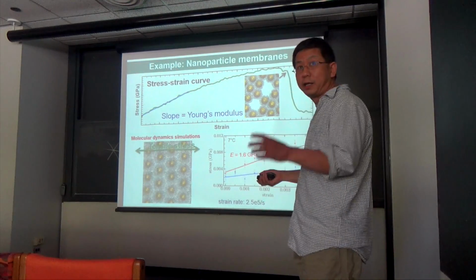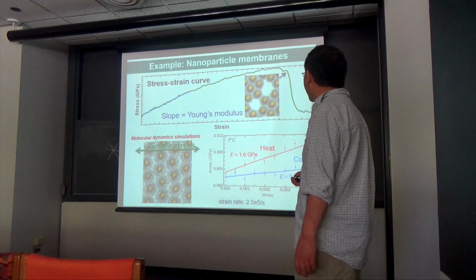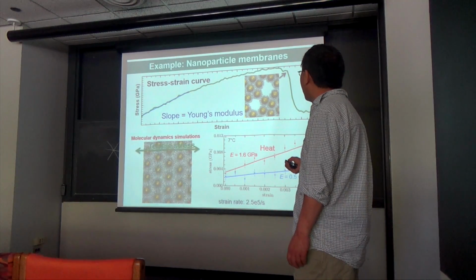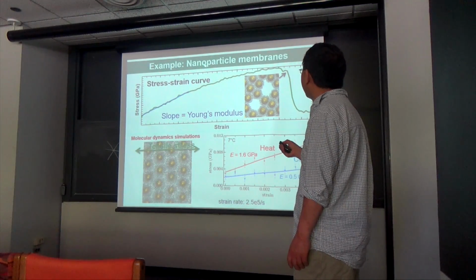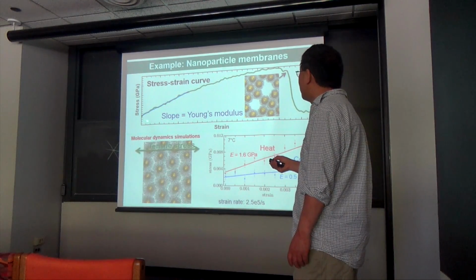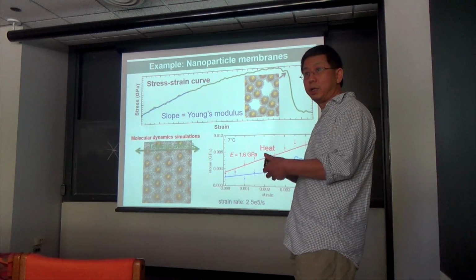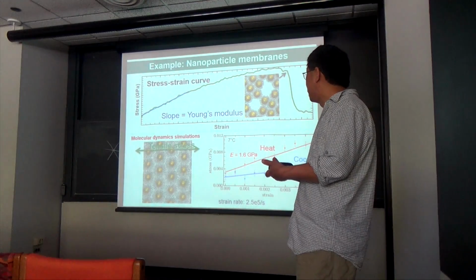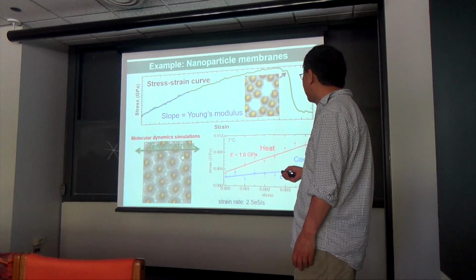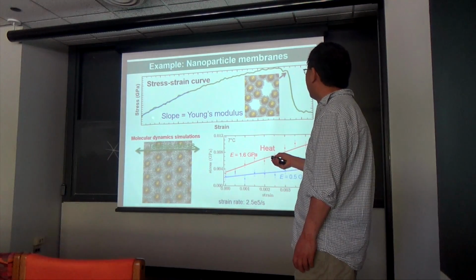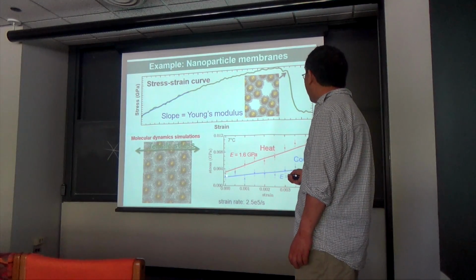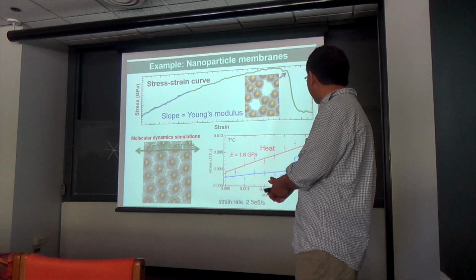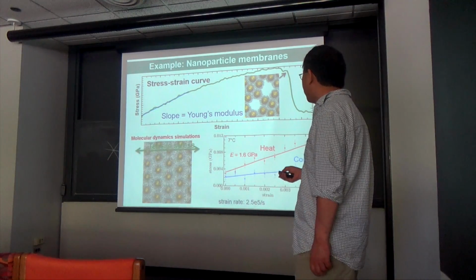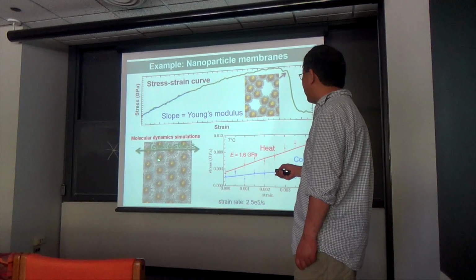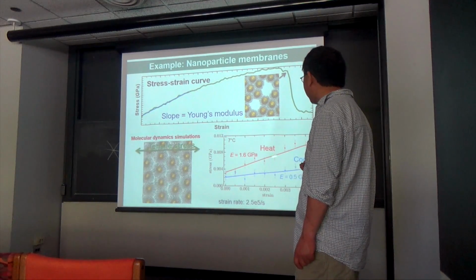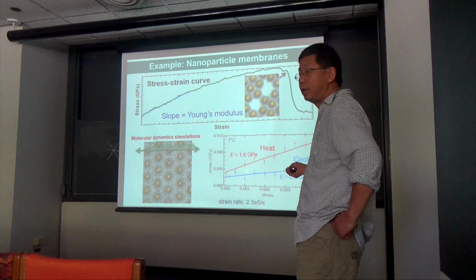So this is an example in collaboration with Heinrich and my lab. Essentially we're using these coarse-grained models to look at the nanoparticle membrane, and we are simulating the mechanical behavior of the membrane as you provide a tensile stress, and calculating the stress-strain curves. And we can find out a variety of things. We can find out how the molecular distributions are related to the hysteretic behavior of some of the things we see in the mechanical